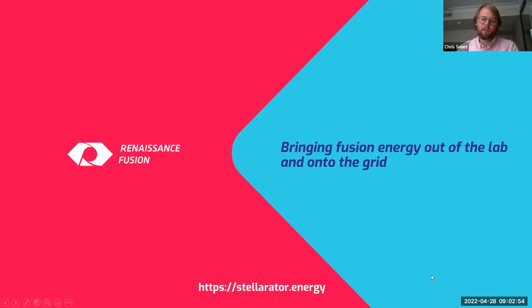So we will need to deposit more than just a single layer of superconductor. The machines aren't finished yet, so we're still working on whether we make it like a spiral with a thick layer of silver in between, or make a white carpet that we roll around. There are different ways to solve it, but we will need to wrap the current around several times. Each band between two grooves will have several layers of superconductor that need to be powered on the inside layer, then go around several times around the stellarator and be extracted from the top layer. So the exact design of the leads is still work in progress.